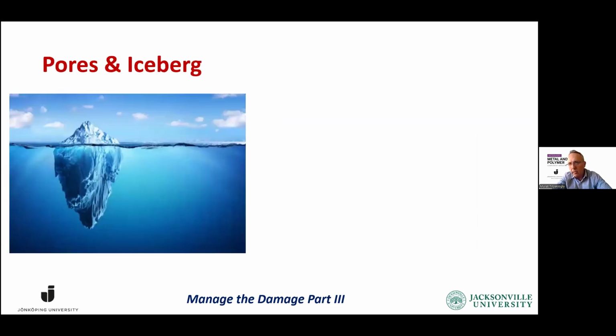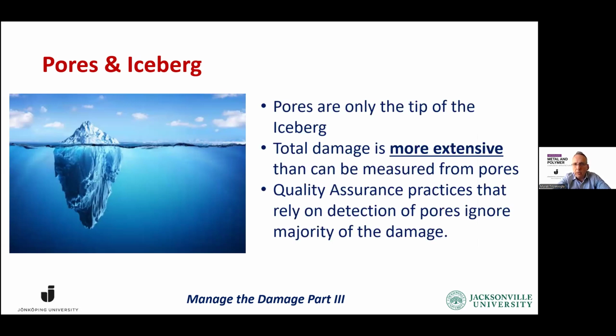So we quickly realized that we're talking about the tip of the iceberg. The pores are only the tip, and the total damage is more extensive than can be measured from RPT or any kind of quality assurance tests. And in fact, quality assurance practices that rely only on the detection of pores clearly ignore the majority of the damage.